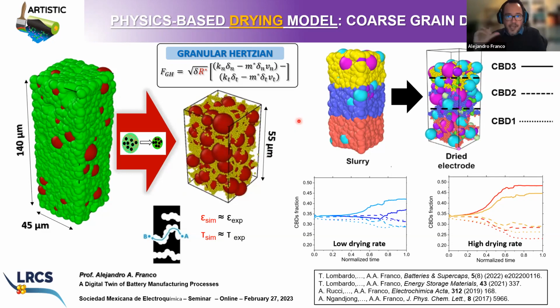When you dry the slurry too fast, what you observe experimentally is that you will have a lot of carbon binder domain going on top of the electrode. And this will be a problem because you will have an isolating layer between the electrode and the separator that I'm going to put on top of this electrode. Here, the simulations are performed by shrinking the CBD at different rates, depending on whether you are talking about the CBD near the separator or the CBD which is in contact with air. CBD here stands for the carbon binder domain, right?